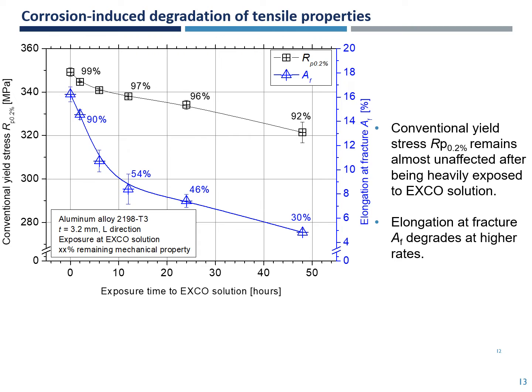Regarding the corrosion-induced degradation of the tensile properties with increasing exposure time to EXCO solution of aluminum alloy 2198 in T3 condition, it was found that conventional yield stress, shown with the black curve, remains almost unaffected after being heavily exposed to EXCO solution, while elongation fracture degrades at higher rates even after short corrosion exposure times.